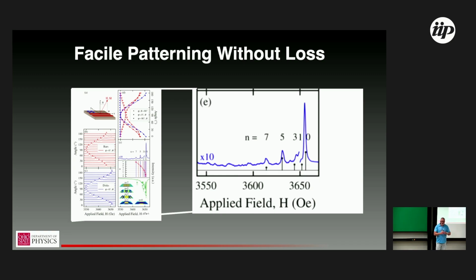It changes as you get smaller, but that has to do with these vortex eddy effects that are actually changing the way the material deposits. It's nothing else. So that means the surface, critically, the surface is not contributing anything to the loss of the magnonics here. So we can design a structure, we can build a structure, we can have faith that that structure will have the same line width and the same damping as we see in the bulk films. And broadly, I think that's pretty powerful.